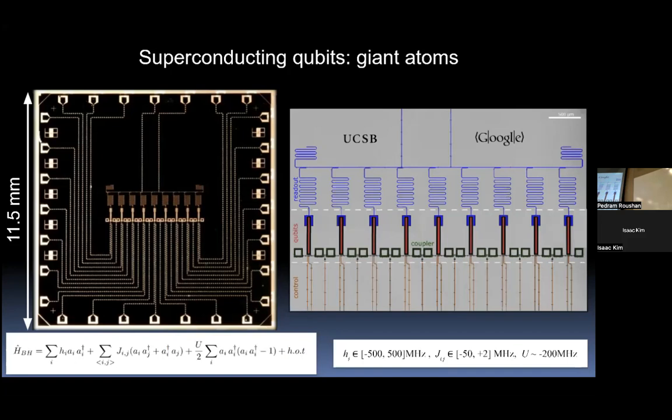You see a capacitor. What you are seeing is silicon with 200 nanometers of aluminum on it, and then you do a lithography pattern on it. Every color you see is Photoshop color. There's no color in there in reality. So this is a capacitor of the qubit, the nonlinear resonator, with the junction I mentioned. And the Josephson junction I was mentioning is a tiny object there. You're not going to see it. And then there's a coupling between them, which is again a bunch of inductive loops.